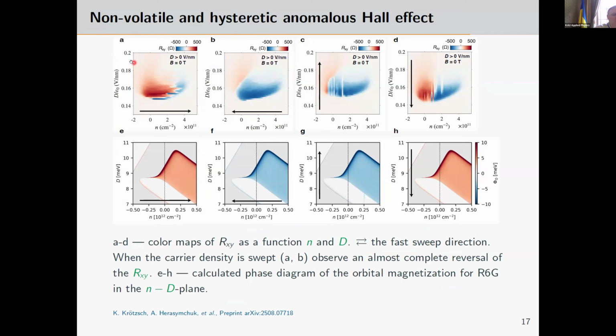We have the Hall conductivity as a function of carrier density and gate voltage. So if I make a sweep in carrier density, it switches to the opposite sign. Then to come back, I should do the switch in the opposite direction. And the same feature appears if I change the gate for the electric field perpendicular to the plane. So again, this hysteretic behavior.